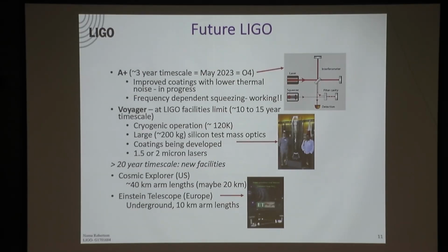Farther in the future, we have something called Voyager, which is intended to live in the 4-kilometer arms and be a cryogenic system. So a prototype is being set up at Caltech. I mentioned that one in particular because it is a cryogenic operation. It's designed to run at 120 Kelvin, and it's going to have large silicon test mass optics, which means it is going to be running not at 1064 nanometers, but at 1.5 or even 2 microns. 1.5 micron lasers exist. 2 micron lasers don't really exist. So in order to make silicon work, it's likely that we're going to have 2 micron lasers. Not just lasers, but quality, stable, et cetera. So that is something that is being worked on.